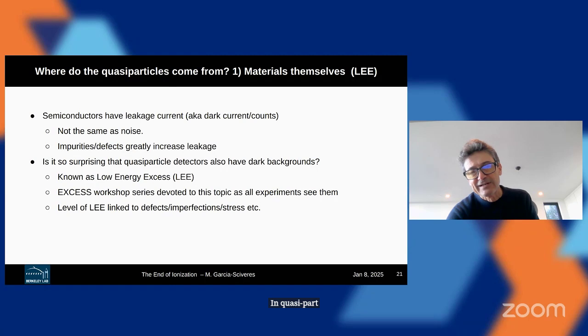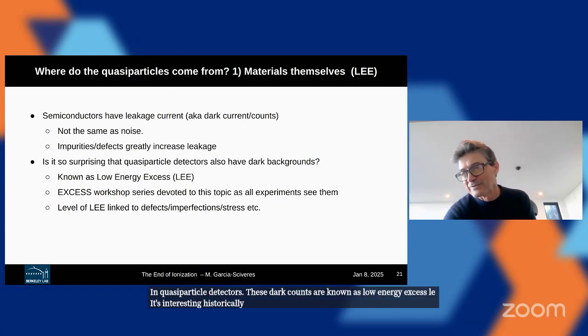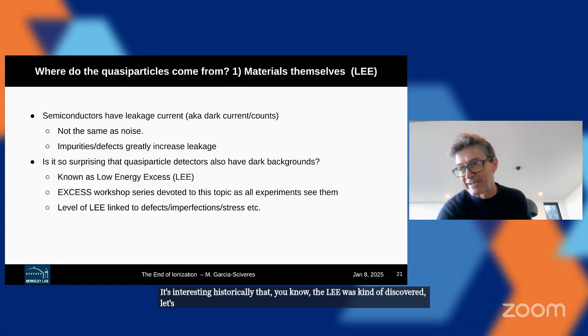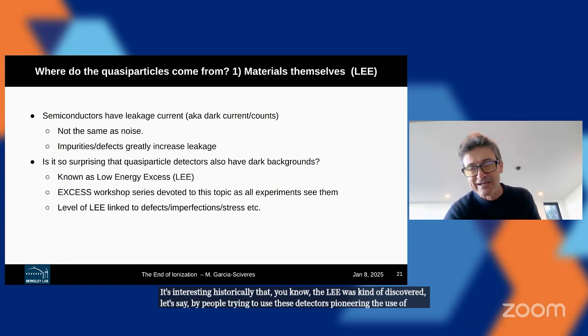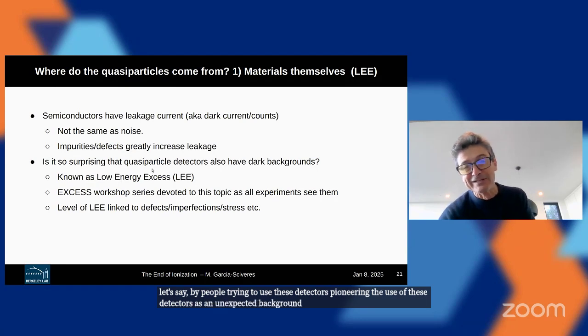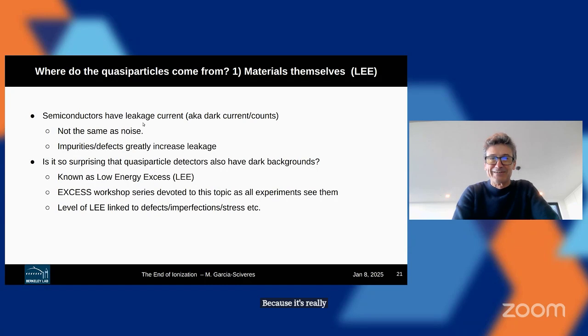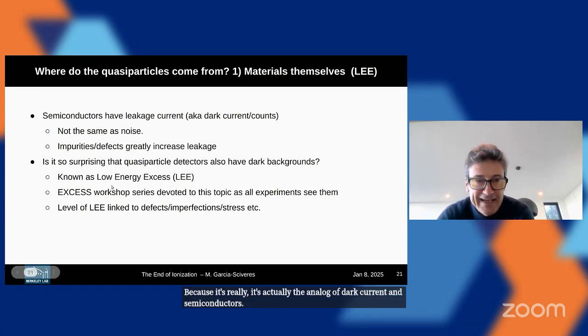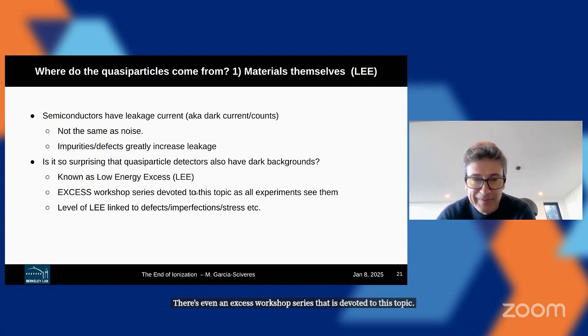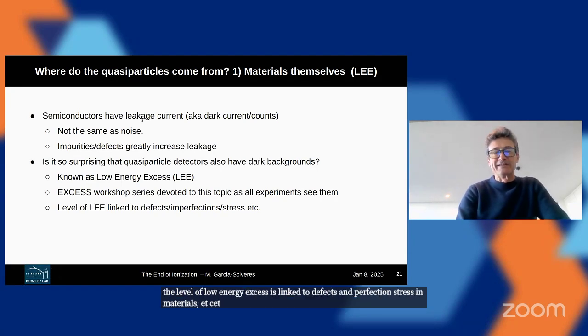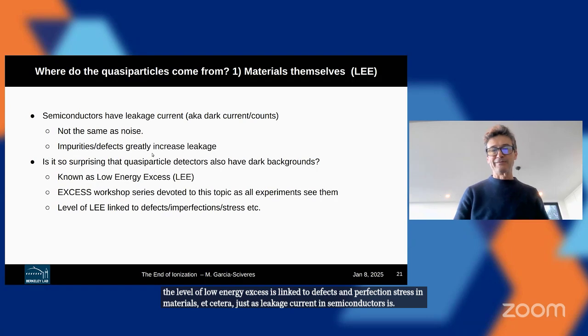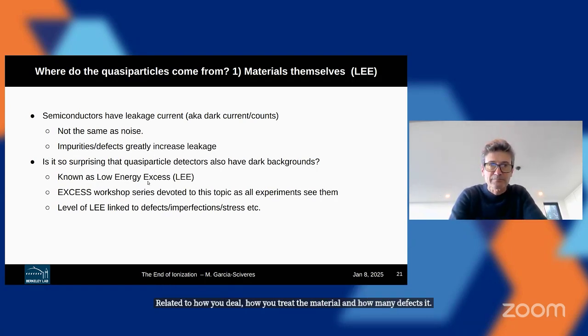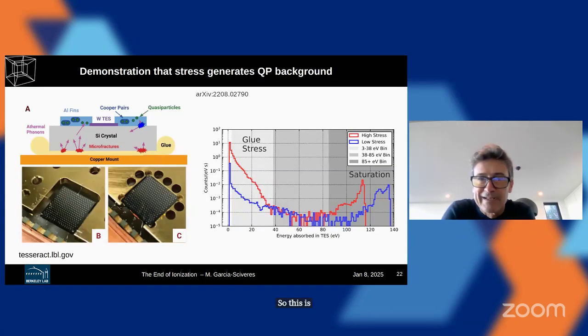In quasi-particle detectors, these dark counts are known as low energy excess, LEE. It's interesting historically that the LEE was discovered by people pioneering the use of these detectors, as an unexpected background. However, it should really not have been unexpected because it's actually the analog of dark current in semiconductors. There's even an excess workshop series that is devoted to this topic. It's all experiments that are dealing with quasi-particle low energy excess. And the level of low energy excess is linked to defects, imperfections, stress in materials, etc., just as leakage current in semiconductors is related to how you treat the material and how many defects it has.